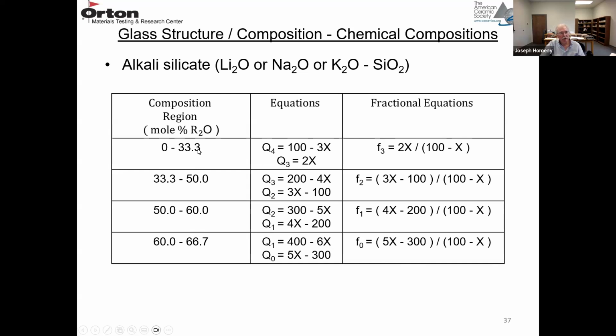So this is X between 0 and 33.3. You put in X here in mole percent, and you can calculate Q4 and Q3. This assumes that as you're creating non-bridging oxygens, they're going to go from Q4 to Q3. So no Q2 or Q1 arrangements are created. So when you add up to 33% R2O and you have all Q3 units, then you start creating Q2 units as you add more mole percent. And then the same thing, once you have all Q2 units, if you keep adding R2O, you'll start adding Q1 units.